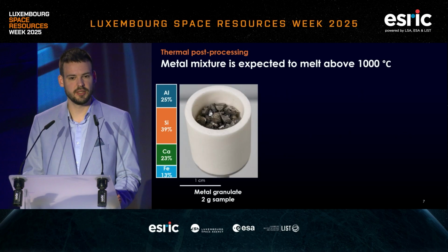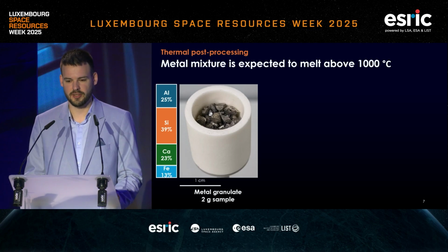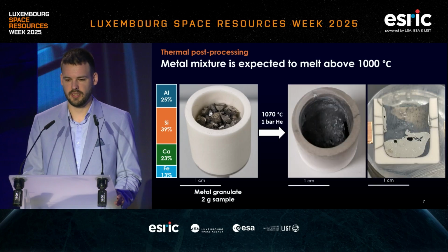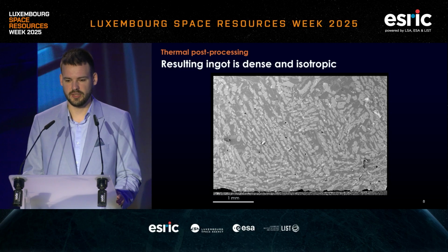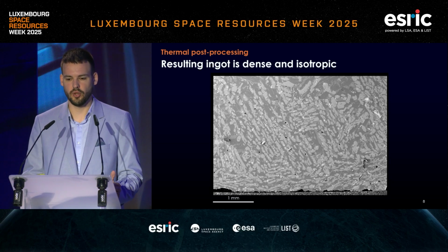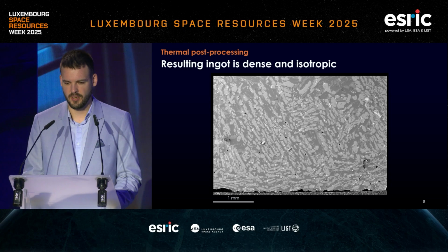So the first thing we did is we took off-the-shelf metal granulates and mixed them in the proportions that we observed in our product. So a mixture of aluminum, silicon, calcium, and iron, and applied different temperatures to it. And we observed that slightly above 1000 degrees C, when we heat it under inert atmosphere, we were able to produce this nicely molten ingot. Here you have a cross-section of it as well. And when we look at it under SEM, we see isotropic distribution of metallic phases, no clear vertical phase separation, and you also see complete consolidation. So it forms a nice melt pool and consolidates to a solid ingot. This is nice.